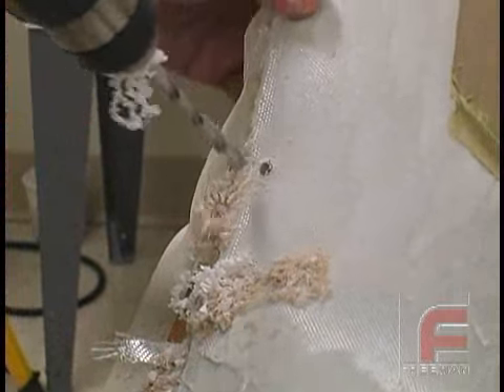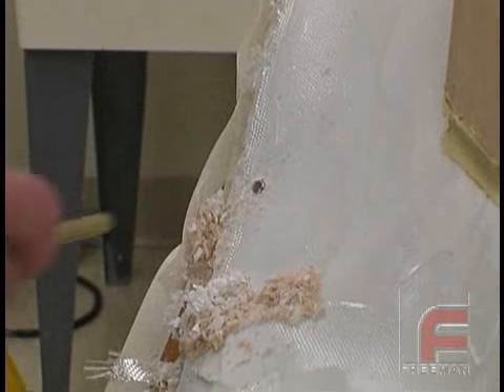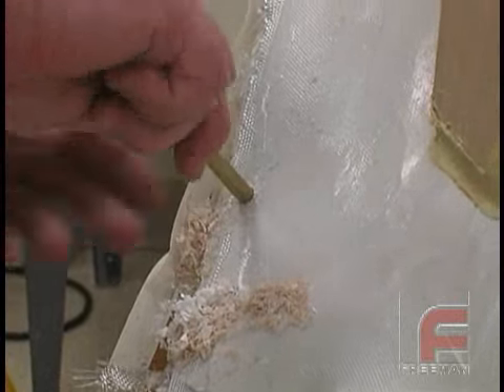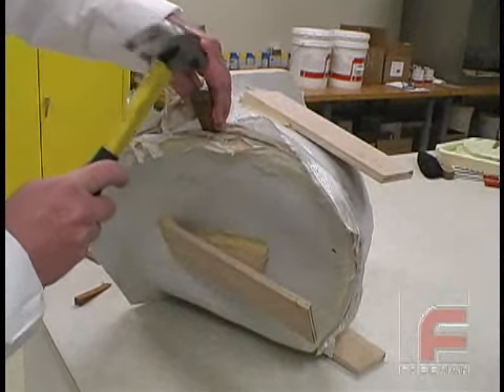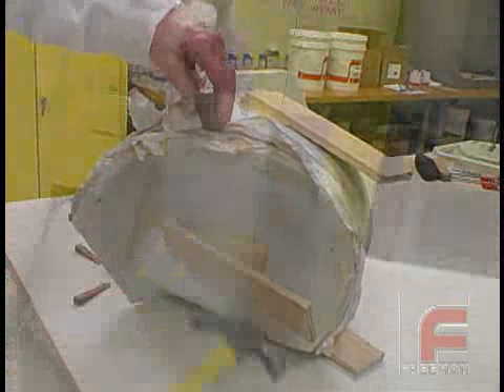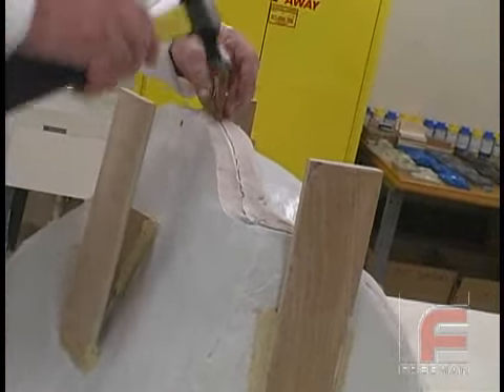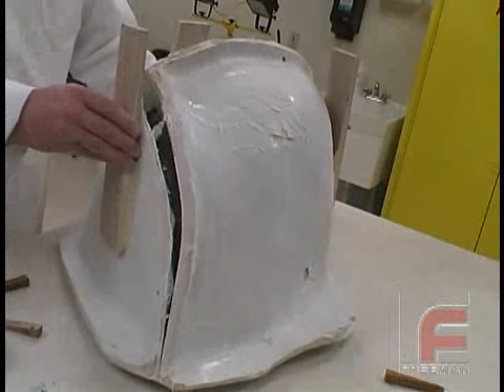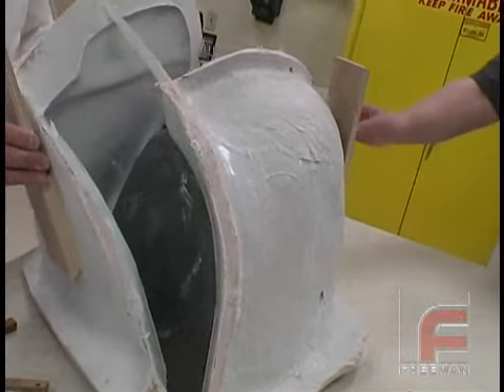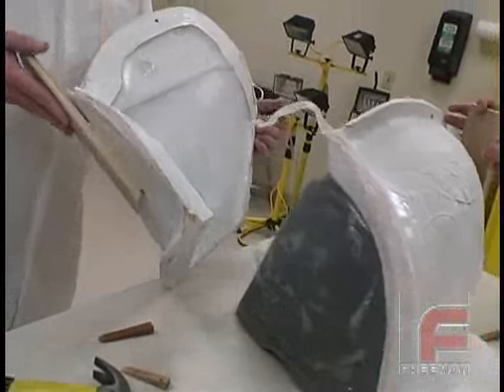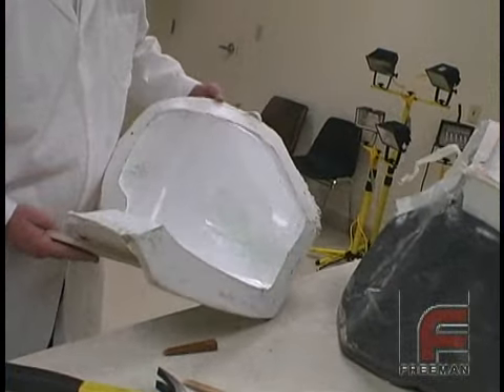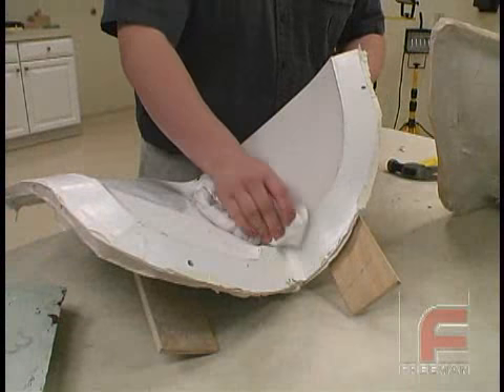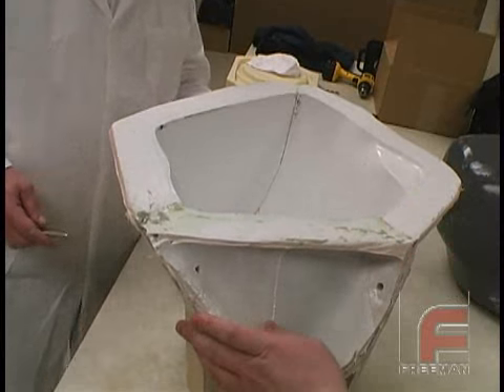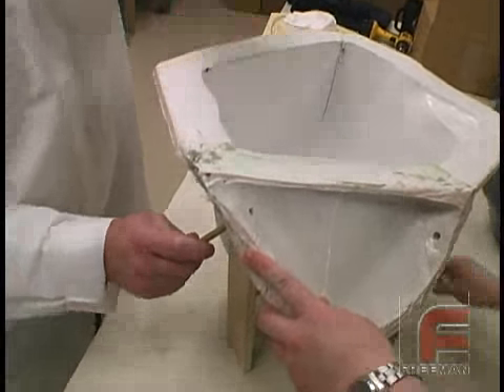Before we demold, we are drilling holes through the lips of our mold to ensure perfect alignment of our three parts later. We are inserting brass dowels into the holes. Here we are placing wedges at the parting lines and tapping them with a hammer. Because we follow the proper sealing and releasing procedures, we are able to demold each part cleanly. Notice the green PVA mold release on our tool, which can be easily peeled off and then washed off with water or a damp rag. Since we drilled the alignment pins before demolding, we are ensured perfect alignment when reassembling our tool.